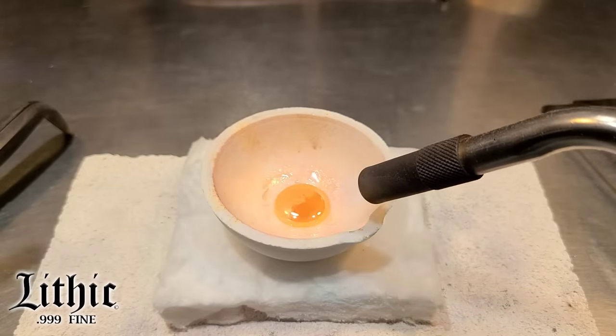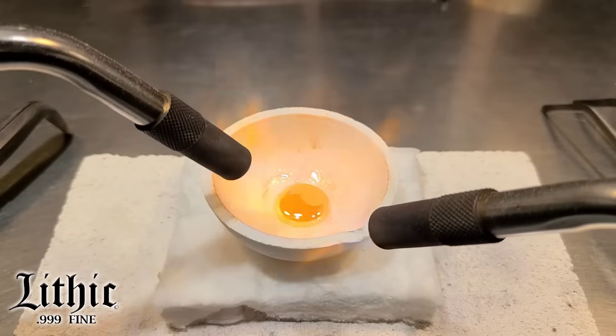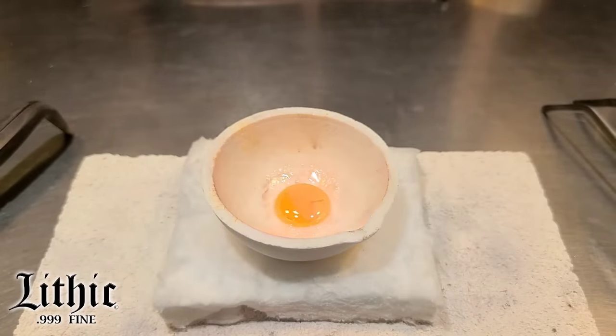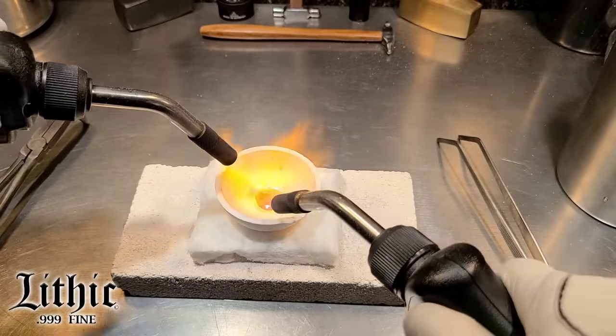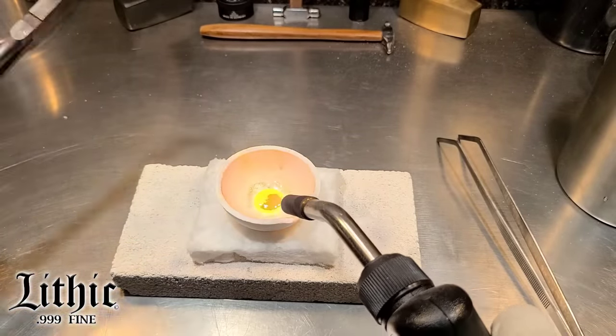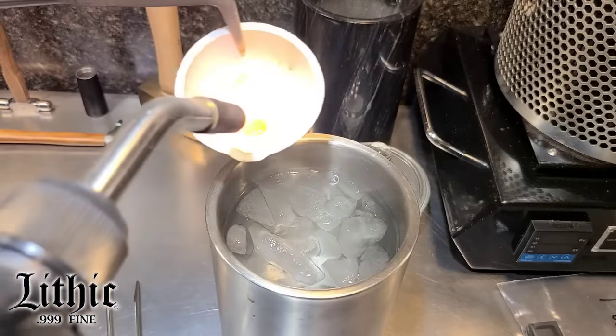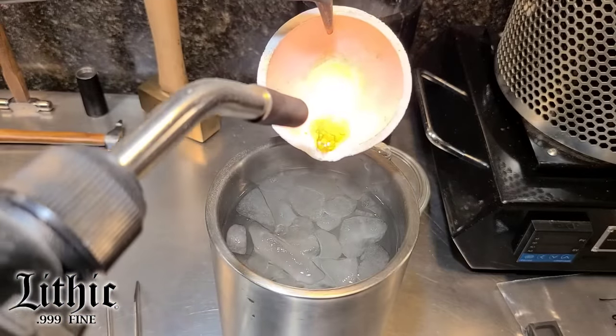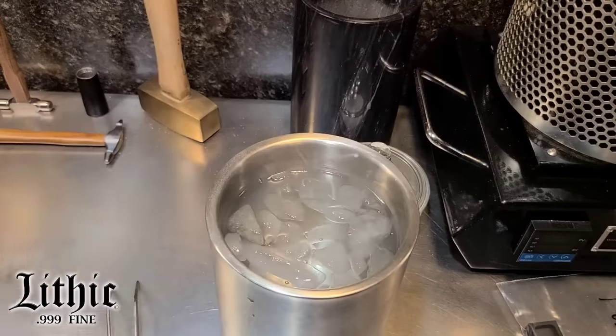I just can't re-pour that, because if I did, those oxides are going to form at the surface of the bar and it's going to look terrible. Those scratches — I think maybe some silver might have got scratched into it. Whatever it was, it's contaminated. So I've decided I'm going to melt it into shot, get it into the booth, and chemically refine this material.